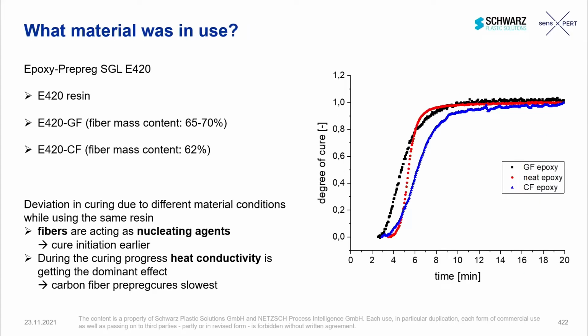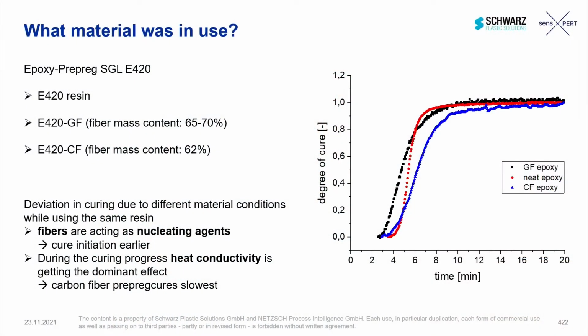Yeah, and to show you a first introduction into what can happen during a production, here we show you an example of one and the same resin system. It's a SGL E420 SnapCure epoxy resin that has been cured within different states. So one time we've cured the pure resin. On the other hand, we have cured the same resin without additional additives in a glass fiber and carbon fiber prepreg. And what you can see here is that with one and the same resin, you have 3 different behaviors of curing. So you can see that the fibers have an effect on the cure process itself.